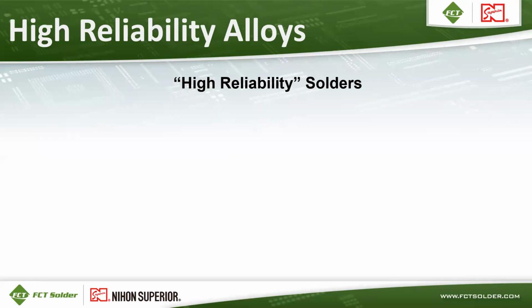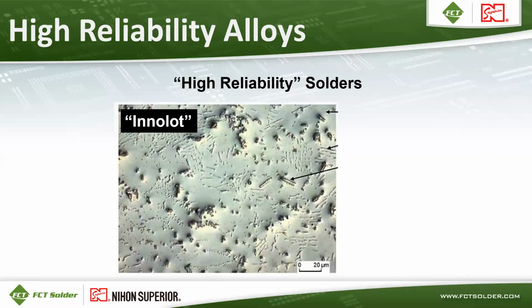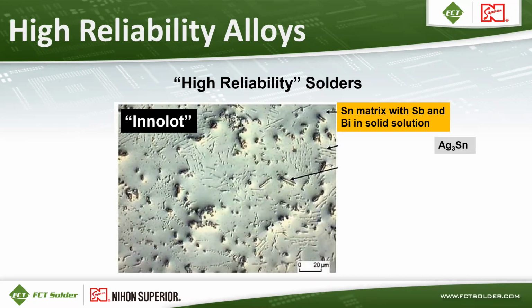So high reliability solders operate based on all the elements that are added to them. Here's a cross-sectional picture of Innolot. Innolot is comprised of a tin matrix with antimony and bismuth that are dissolved in solid solution. It also has Ag3Sn intermetallic particles that look like whiskers or dendrites within the solder matrix. And then it has Cu6Sn5 intermetallics as well, which also are solid particles in that solution.